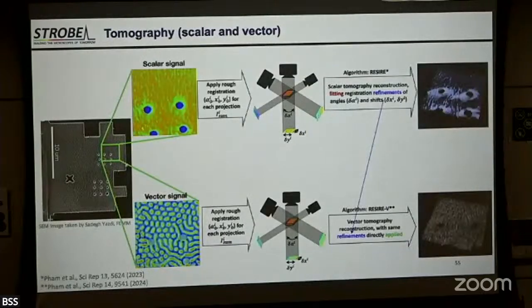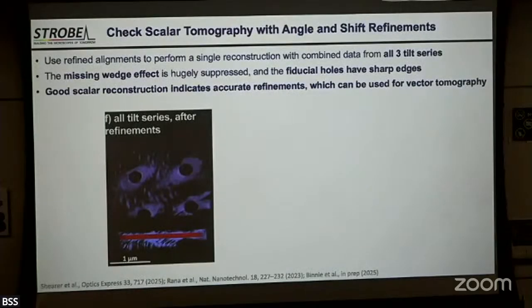And then the next trick is every time you took the sample out, you put it back in a slightly different position. So you have to do something called image registration, and you have to move it around. But after you do everything right, of course, there should be no contrast in the scalar image, but you have a little bit of contrast because of missing wedges, and the silicon nitride membrane was rippled, and that's what you're seeing here on the left.